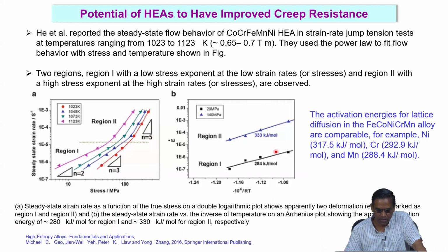The important point to note here is that the activation energies for lattice diffusion in this iron, cobalt, nickel, chromium, manganese alloy are comparable. For example, for nickel it is 317.5 kilojoule per mole, for chromium it is 292.9 kilojoule per mole, and for manganese it is 288.4 kilojoule per mole. So you can see that these values are very close to what is calculated for this particular alloy. That means you can say that lattice diffusion is the primary mechanism here.